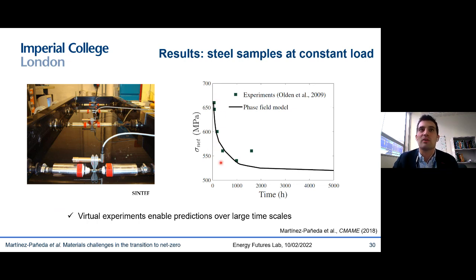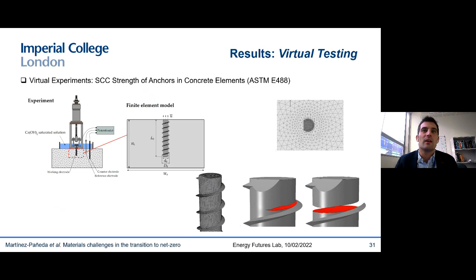So if the stress is low enough, then there's no issues. But as you can see, the symbols are the experiments. All of them failed at a relatively short time from an engineering perspective. But the good news is that we can take our model, we can not only reproduce our experiments, but also run virtual experiments over very large timescales and tell engineers what is that critical load below which they can load without embrittlement issues.